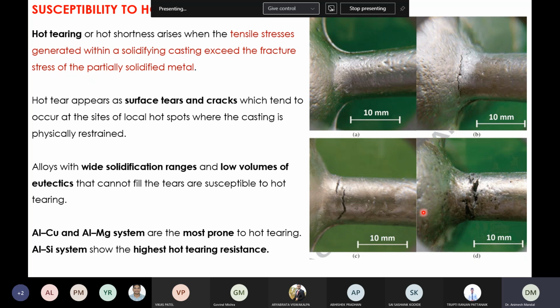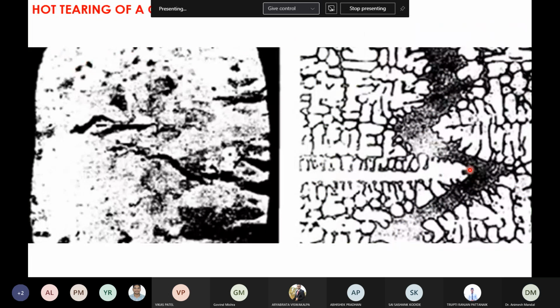So it is also a function of the system. How do we then make these aluminum copper alloys? If you end up always getting hot tearing, you can tailor your composition in such a way, and design your molds in such a way, that you can avoid this. It's mostly a system specific problem, meaning which system we are talking about. Obviously, it can sometimes occur due to a faulty mold design, but that can always be corrected. But you need to be sure about this condition. The mold and alloy composition also have to be chosen appropriately so that you don't end up having all these defects.